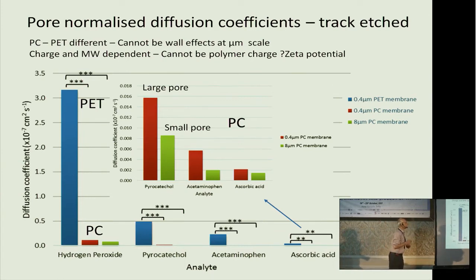These are diffusion coefficient values, and they are for the polyethylene terephthalate membrane, which was one of the track etch membranes, and polycarbonate membrane. And if you look at the diffusion coefficient values here for peroxide, this material has zoomed up diffusion coefficient. This is totally not acceptable, totally counterintuitive. It's also got diffusion coefficient values for the other molecules, which are much, much lower. But these are micron-sized pores. This is not credible, not possible. And there's also resolution based on large and small pore size, which is just weird.